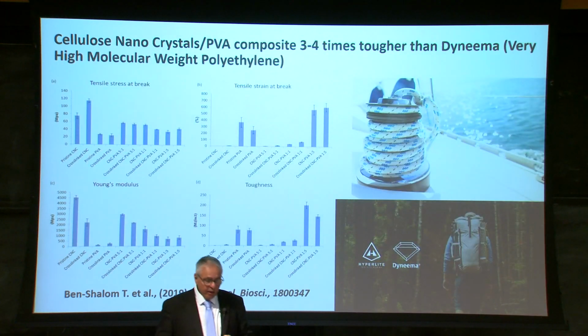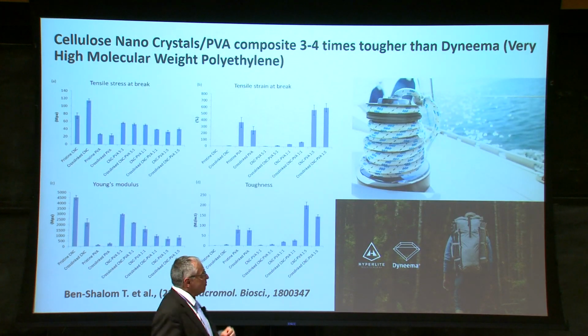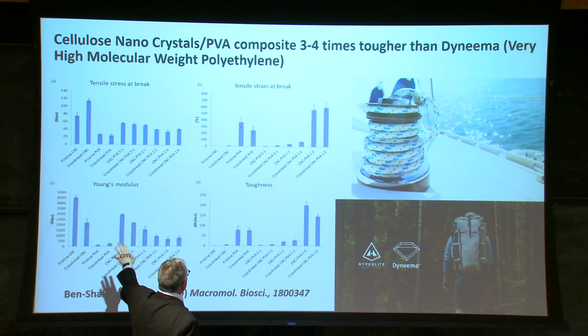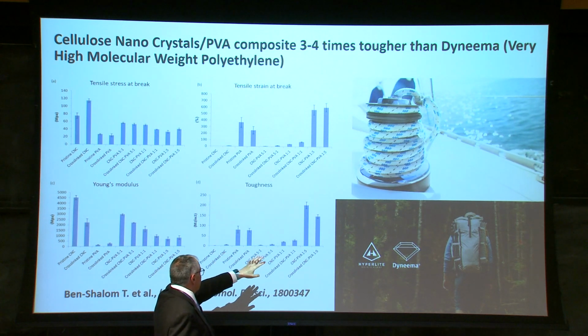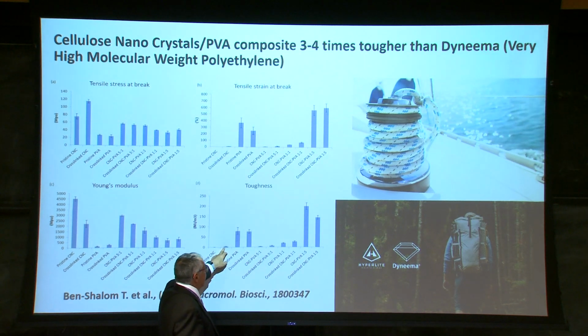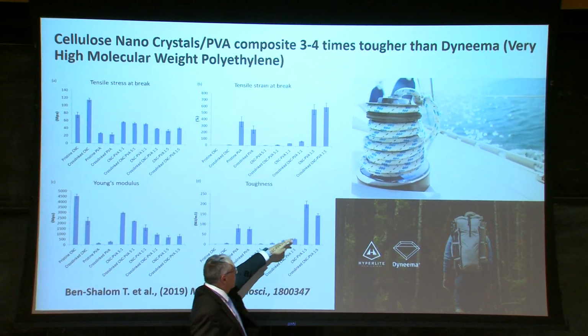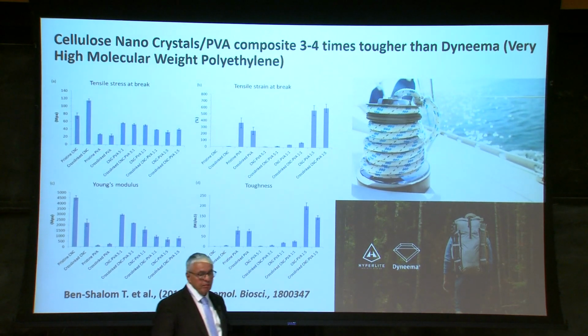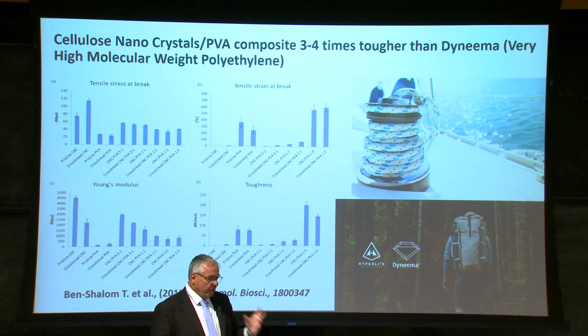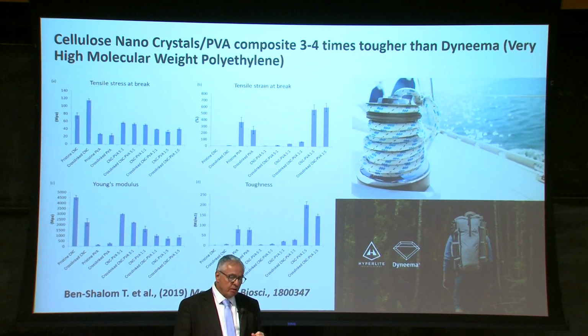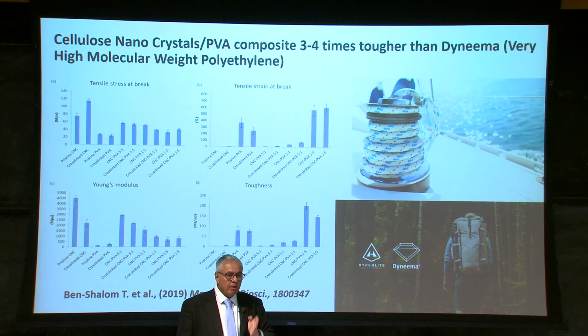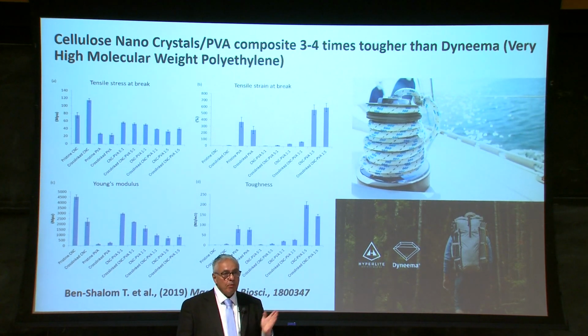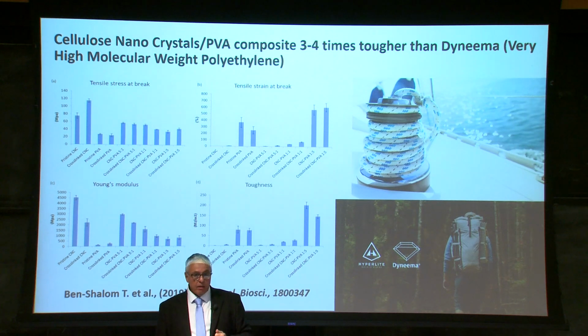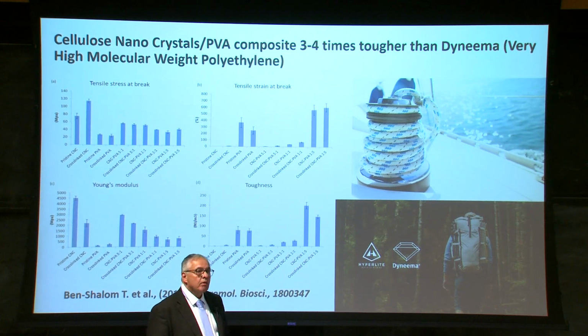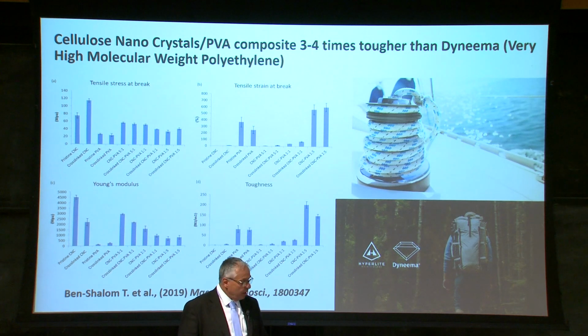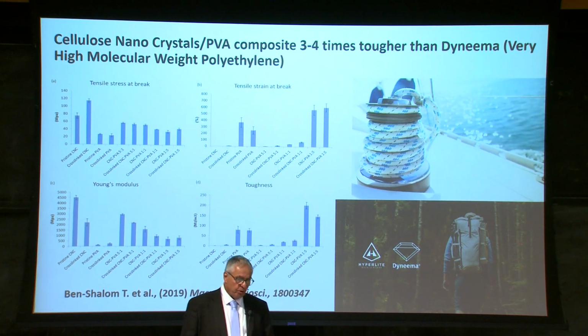The most striking thing is the mechanical properties. And I will not go through all of them, but just mention the toughness. This is crosslink CNC, the toughness, and this here is CNC PVA 1:5. Just to give you a feel, the toughness of this material is 3 to 4 times tougher than Dyneema. Dyneema is very high molecular weight polyethylene, which is used as ropes and also some sport goods. So very, very strong material.